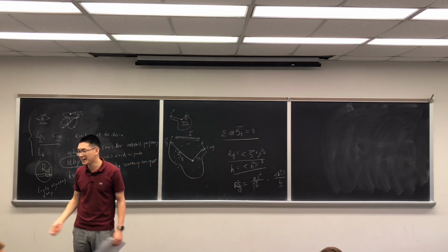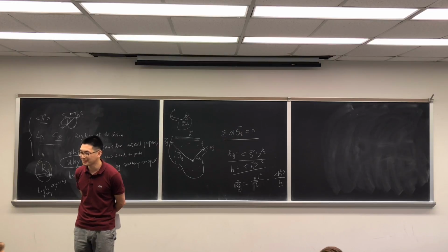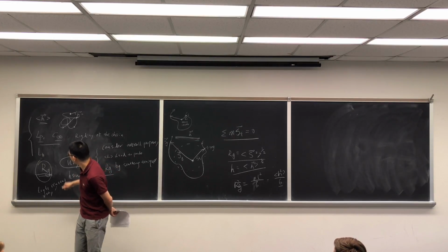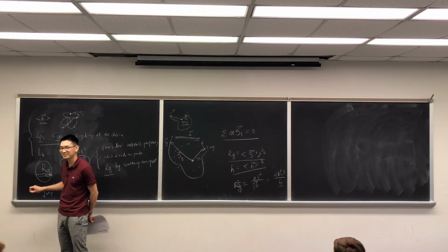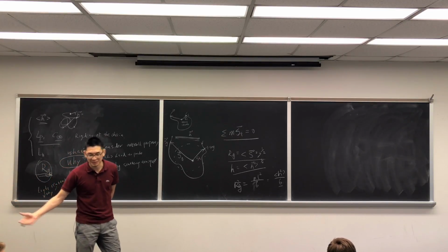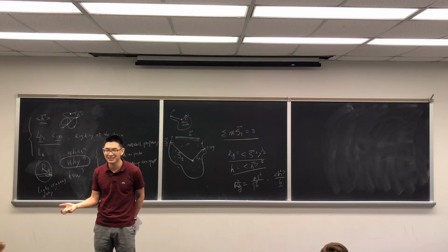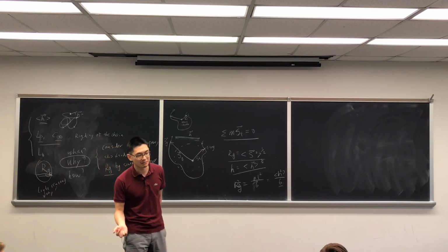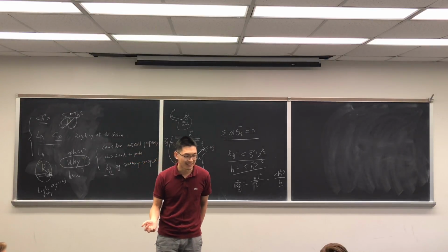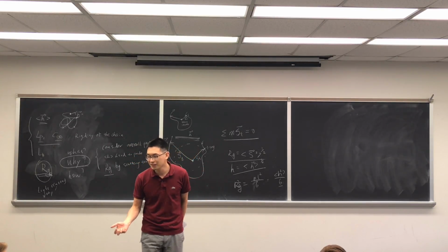So in the end, it's a happy ending story, because if you measure Rg, you do light scattering, you make a polymer, you dissolve it, you do light scattering, you get the Rg. Let's say an arbitrary number is 20 nanometer. Then you know what the end-to-end distance is.